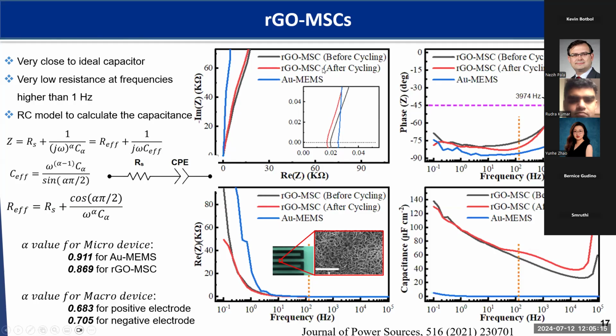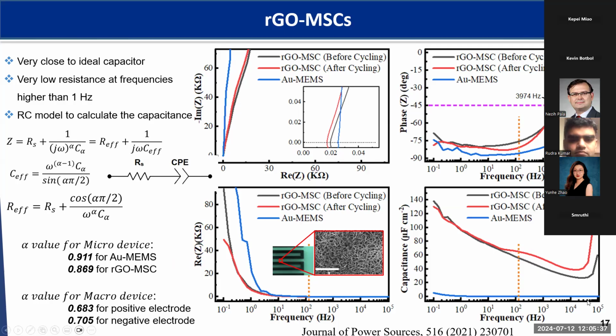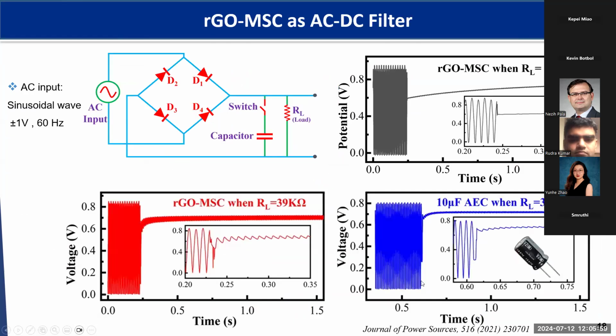And we also did some modeling work trying to understand from another concept, the fractional capacitor concept. We try to quantify how good our RGO-based capacitor is compared to the gold electrode-based capacitor, because that has an almost perfect 90 degree phase angle. So our capacitor is pretty good, and the capacitance is much higher than the gold, because gold doesn't have enough surface area. You can see the capacitance is almost zero at different frequencies. But for the RGO-based microcapacitors, even at very high frequency, we still can maintain high capacitance. So that's one of the best microcapacitors we have.